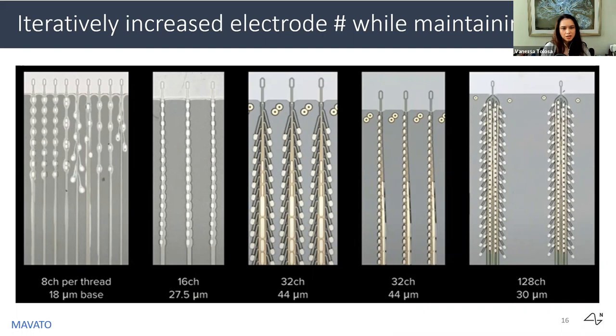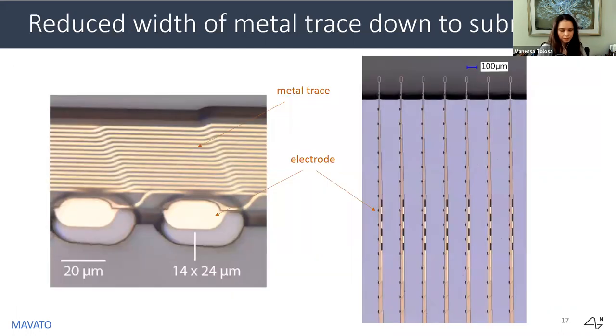And the shiny dots are the individual electrodes. Remember, for every electrode, there's an individual wire attached to it. That's very difficult to see from here. From left to right is the progression that we made. We were able to increase the number of electrodes per thread from 8 to 128. But you can see that the width of the base of the probes didn't even double going to these larger sizes or channel counts. So how did we increase the number of electrodes by 16 times, without even doubling the width?